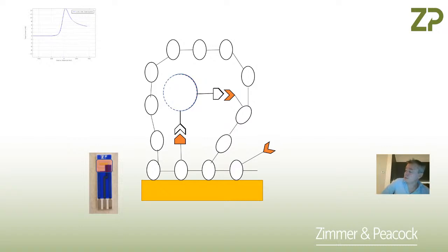And if your template has functional groups on it, like amine groups, carboxylic acid groups, alcohol groups, you can then use a mixture of monomers which will bind to that template and those functional groups. Then when you polymerize it, you hope to create an imprint which is the right size of the template and has specific group interactions. Then you wash the template away, and you're left with what I'm calling a catalytic site. It's like an enzyme's catalytic site, but rather than being catalytic, it's just a binding site. So maybe the better analogy is actually an antibody.